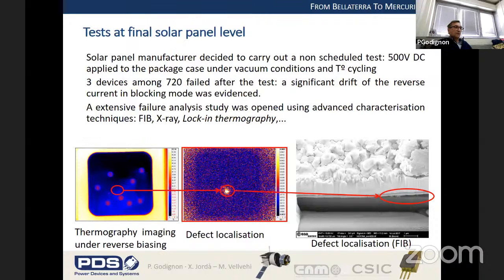Thermography imaging of the top of the device allowed us to identify a hotspot on the failing device. And again, doing a cross section in the area of this hotspot, we could see that there was effectively an important problem: the metal lifted from the surface of the silicon carbide, creating this damage.